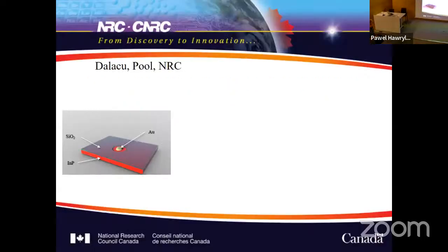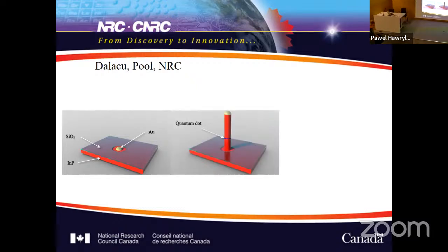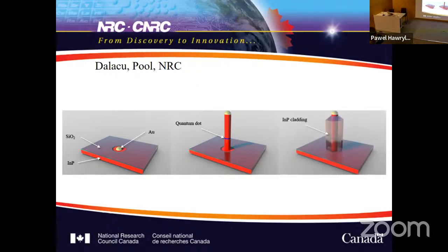So this is the basis of technology from Dan Dalacu and Philip Poole, my colleagues at NRC. You start with an indium phosphide substrate. In a specific location, you put a gold nanoparticle in this opening, and then you deposit indium phosphide. You start depositing indium arsenide, and you create a quantum dot in an indium phosphide nanowire. The nice thing is you can clad it, and then you have this quantum dot coupled to a photonic cavity that can be directly coupled to an optical fiber. Yes, it's all indium phosphide. Remember, to couple to the telecom network, we need to work with indium phosphide.